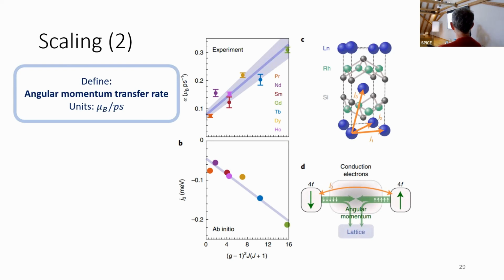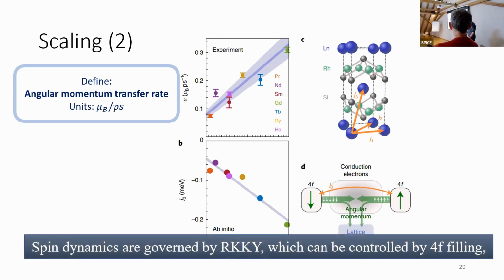I'm sure somebody will be upset at me about this, but the key understanding here, if you look at this diagram, is that if you have one 4f site and another 4f site, the coupling goes through the conduction electrons, of course, and angular momentum is transferred through them, but not perfectly. Some of it goes to the lattice. And this is what we see here. This is a rate that does not actually depend on the 4f filling. In other words, it does not depend on the overlap integral between the 4f's and the conduction electrons. So our conclusion from this is that spin dynamics are governed by RKKY, and we can control it with the 4f filling.